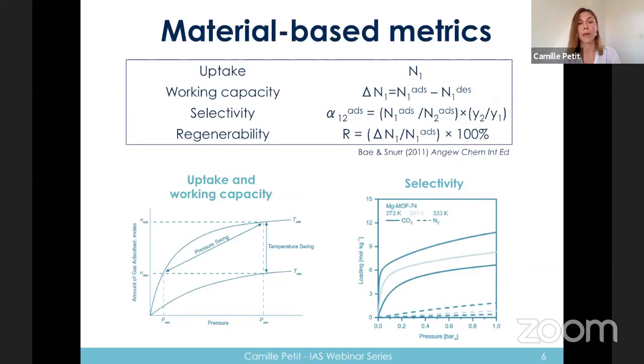And the first kind, I would say, is materials-based metrics. And we can think, for instance, of the uptake. So if we consider the graph at the bottom here on the left, we have an isotherm at 2 different temperatures. So it characterizes the amount of gas adsorbed as a function of pressure for 2 different temperatures. And the uptake would be the amount of materials you have adsorbed at a given pressure and temperature. We can then consider the working capacity, which would be the difference between the amount adsorbed and the amount desorbed for a given, again, temperature and pressure condition.